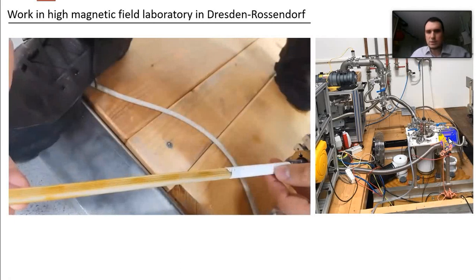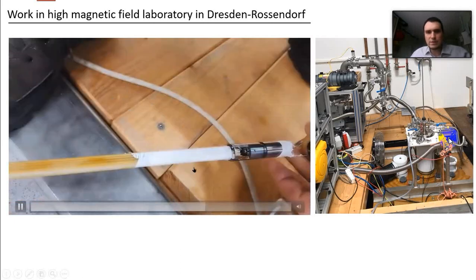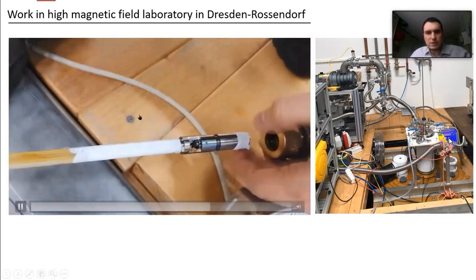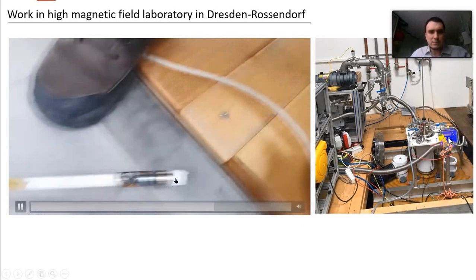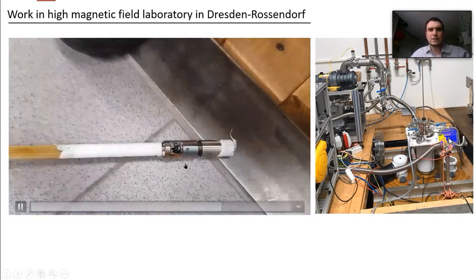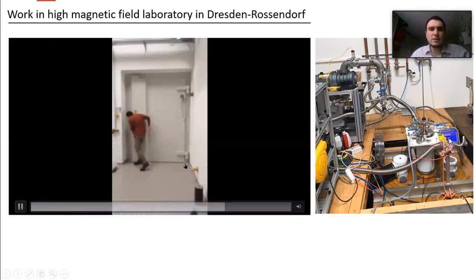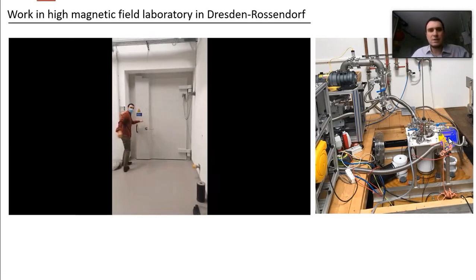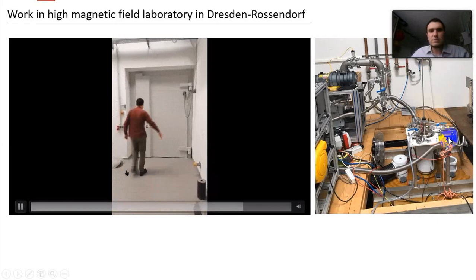Okay, and this is, yes. So this is the diamond anvil cell, and in the center of the cell, you can see the sample. So two diamonds, and between them, the gasket is squeezed, and inside there is a small, tiny sample, about 30 microns in diameter.